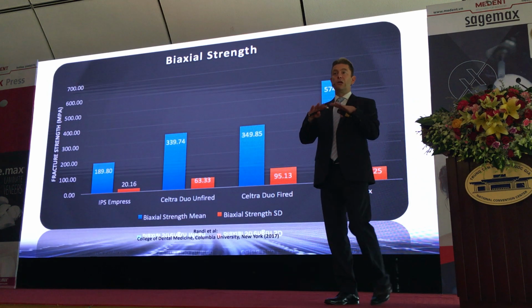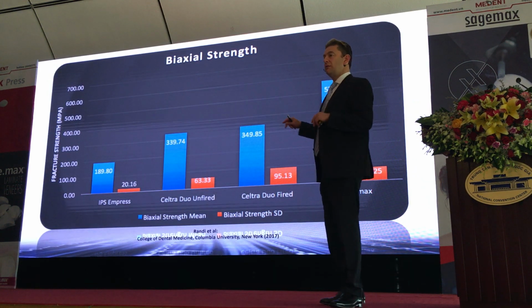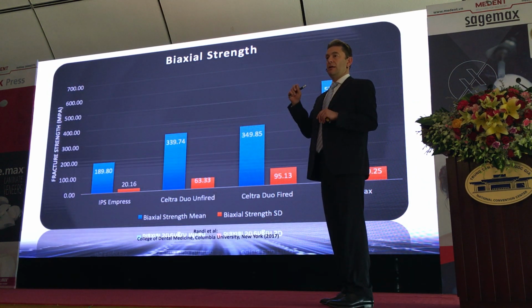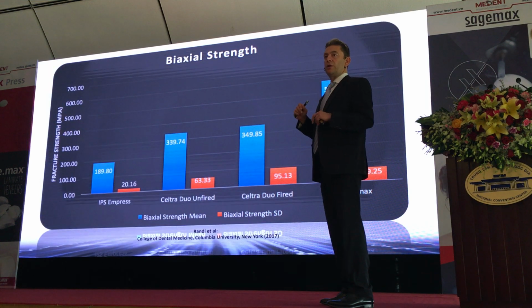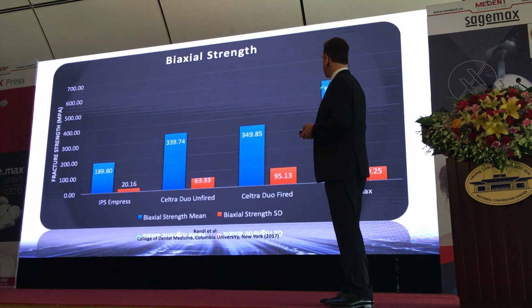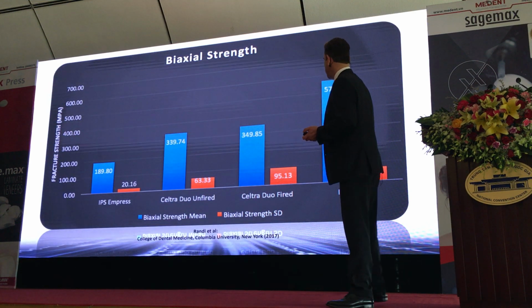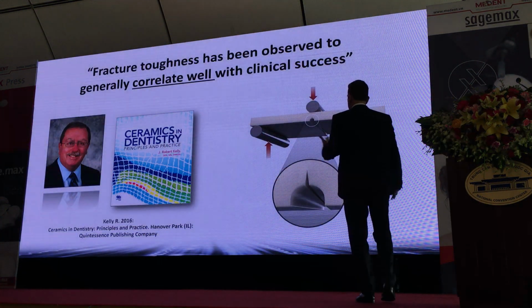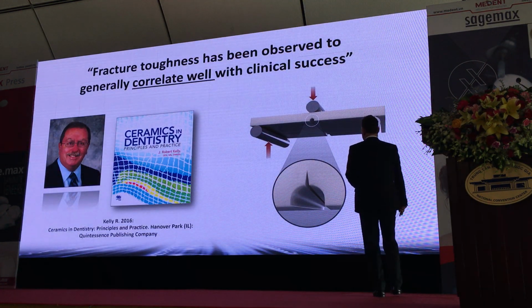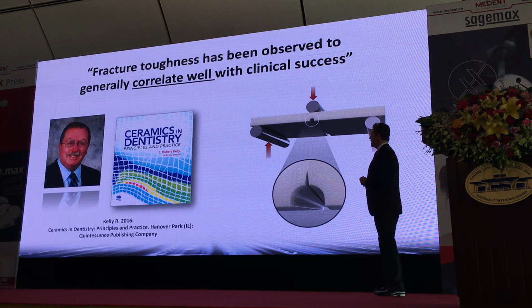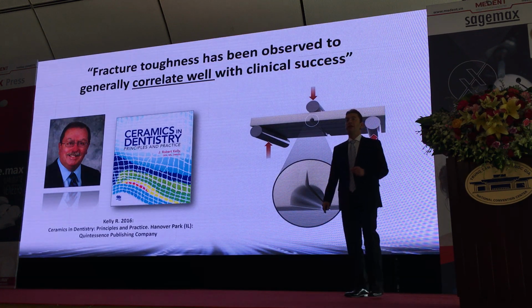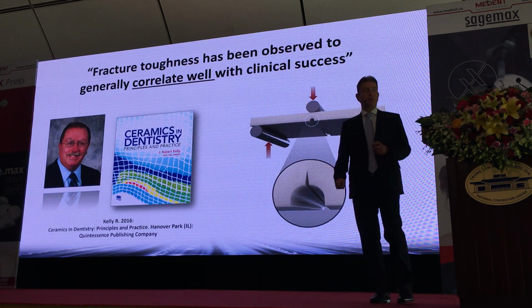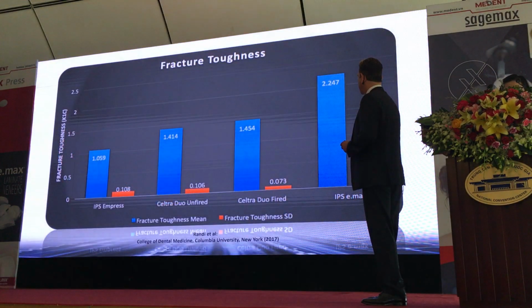Even though it looks like a very similar material, and even Celtra, they claim has some zirconia inside, you can see the strength is not as high as emax. And the other test, the fracture toughness, has been shown to correlate quite well with the clinical performance of the material. And this is why we check it here.